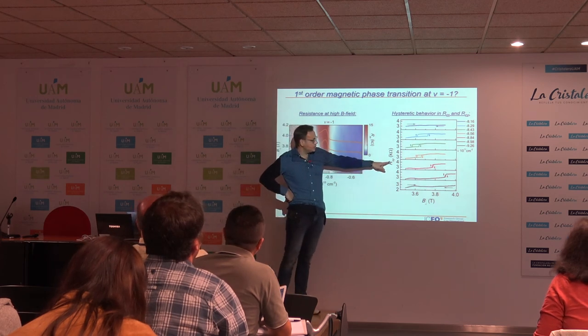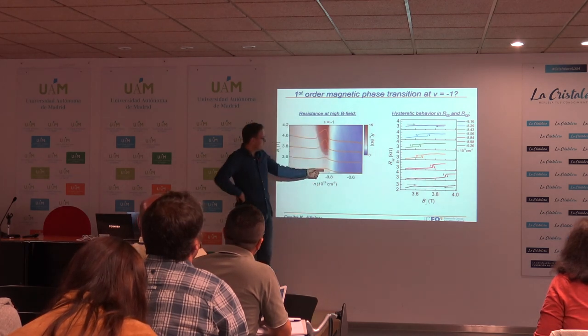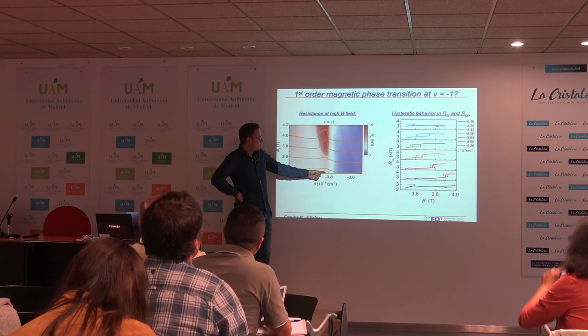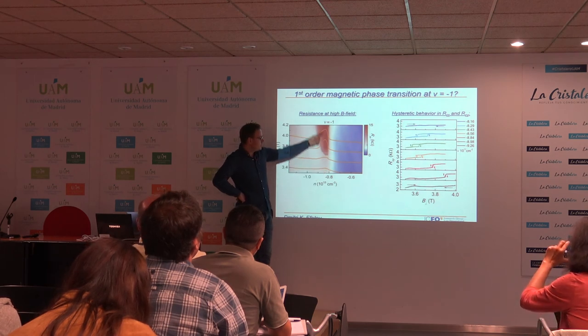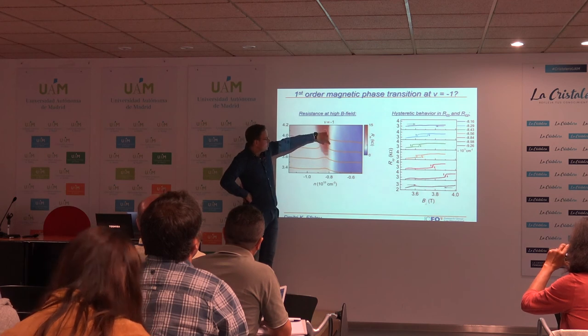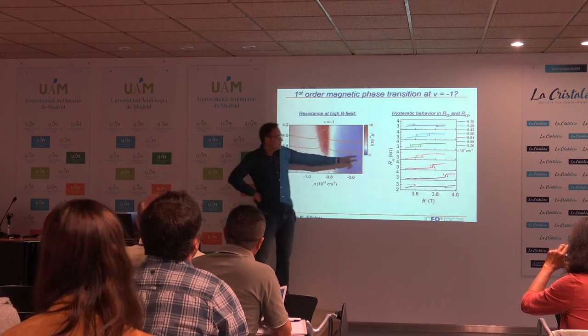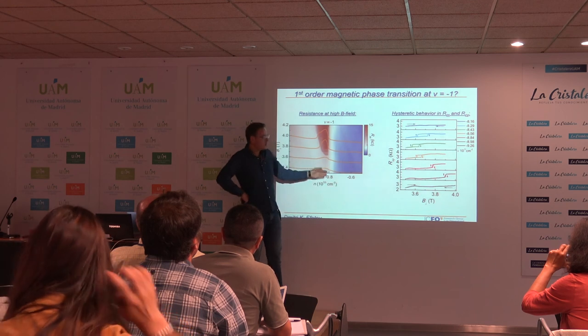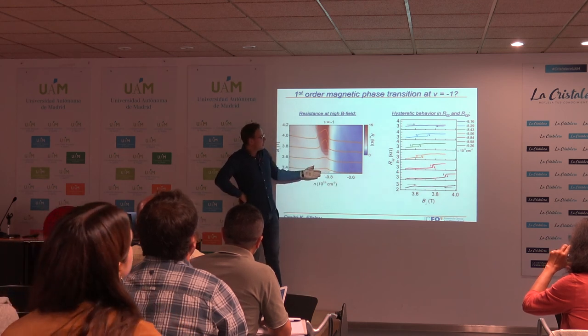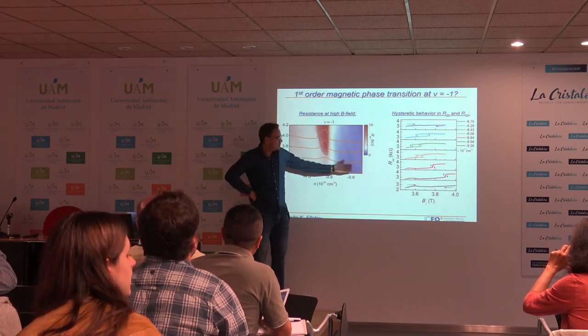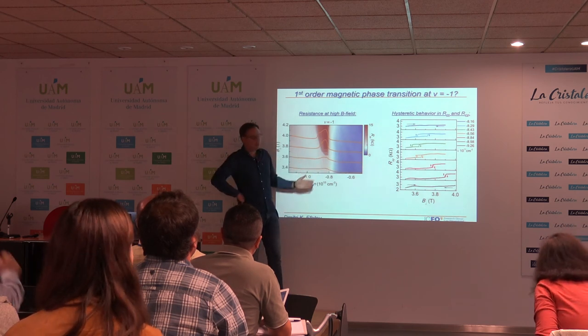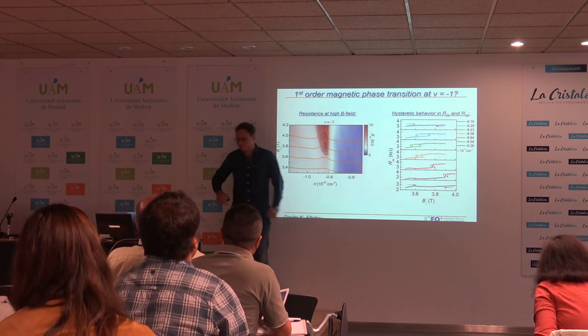This is a measurement of Rxy exactly around the minus one electron per unit cell filling. We can see that in this narrow region around exactly minus one, we see a magnetic hysteresis when we sweep the magnetic field up or down. And this magnetic hysteresis disappears when we go to higher densities, left and right from the integer filling condition.